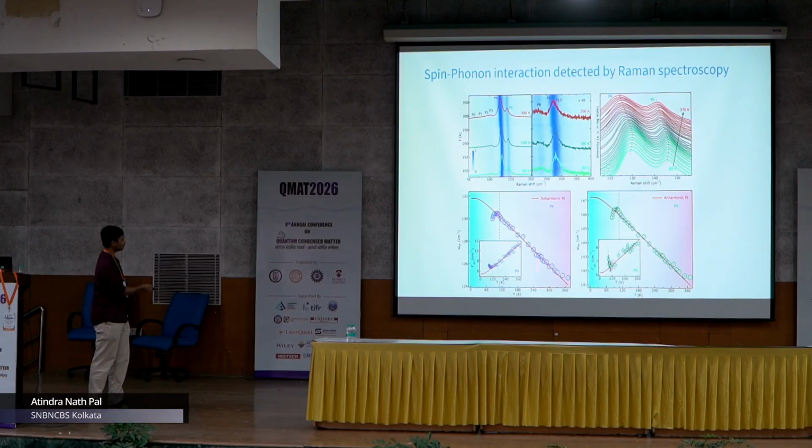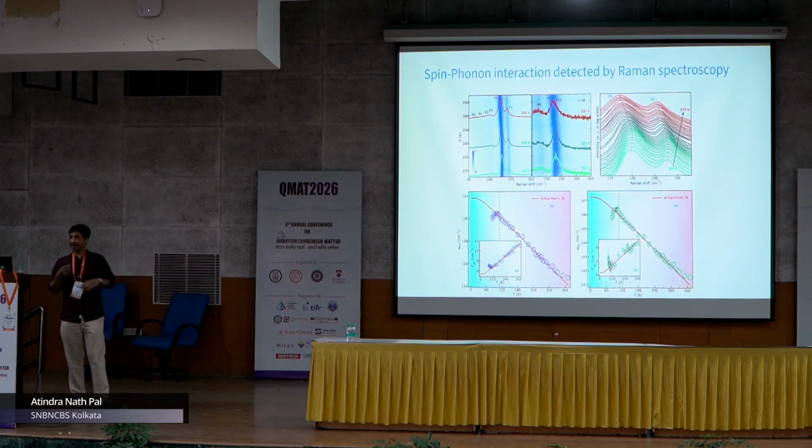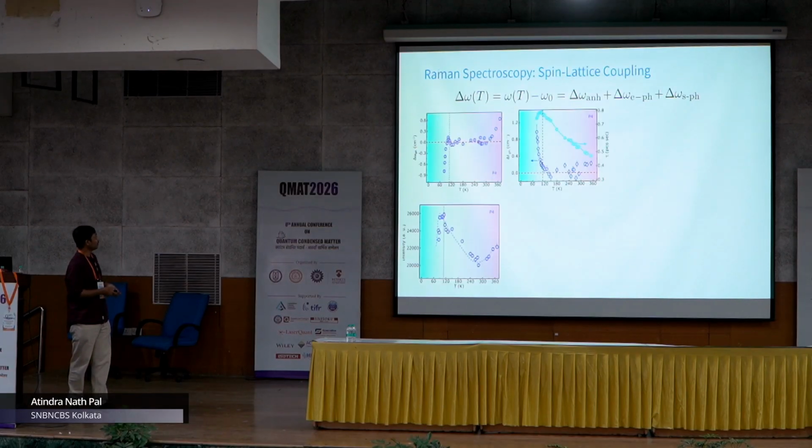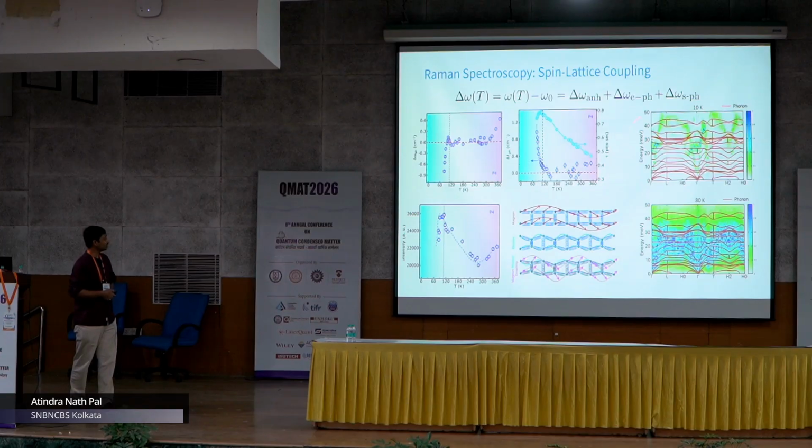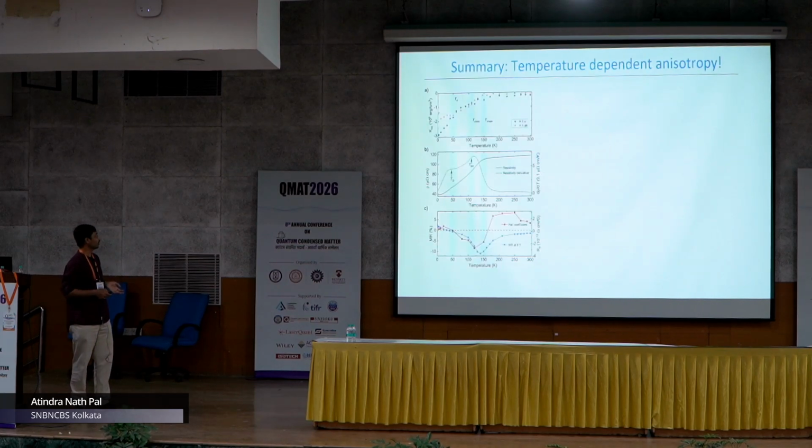Although near the ferromagnetic transition there is not much effect, near the spin reorientation transition, which is another magnetic transition, the effect is pretty high. We have done all the detailed calculations of the Raman modes in our arXiv paper. They also found, through theoretical atomistic spin dynamics calculations, magnon modes below the spin reorientation transition, and we are certain that there is a strong spin phonon coupling near the spin reorientation transition.